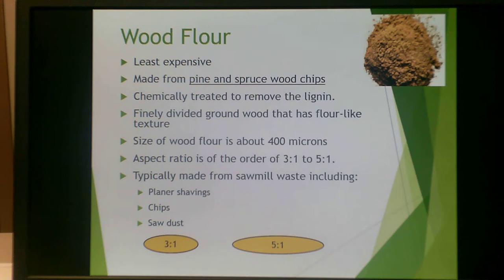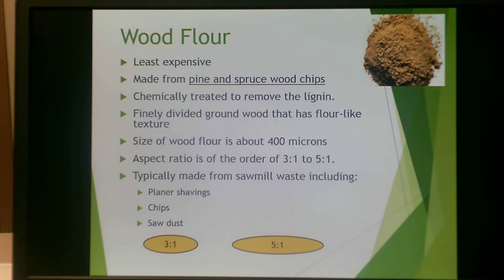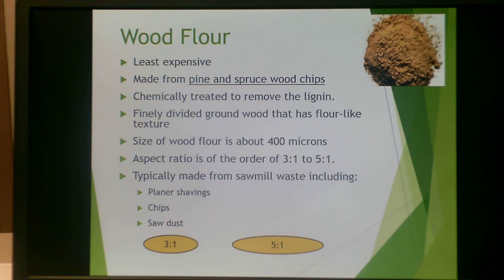The first of these fillers is wood flour. This is the least expensive of the typical fillers, and is generally made from pine and spruce wood chips that have been chemically treated to remove lignin. It is then finely divided into a ground wood that has a flour-like texture. The size of the wood flour is about 400 microns, and it very closely resembles wheat flour in texture. The aspect ratio of the individual particles is 3 to 1 or 5 to 1.